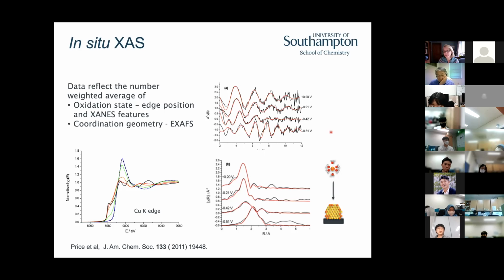If we then isolate the EXAFS spectrum, what we see is, when we're up at plus 0.2 volts in this case, we really have the copper ions in solution. Then as we go negative, we're depositing the copper onto the gold surface. The frequency of the oscillations has to do with the coordination distances. The decay in those oscillations, how they decay as we increase in k space, this is k, in angstroms to the -1, which is an energy space. Initially the oscillations decay very quickly as we go out into k space. But when we've made the copper atoms sit on the gold, you can see that it's extended these oscillations.